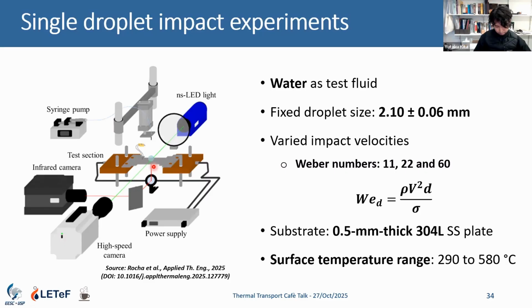Another important detail regarding our technique is that we do not need to know the emissivity of the black ink, because we use a thermocouple. At the same time we measure with the infrared camera, we have an insulated thermocouple on the top.